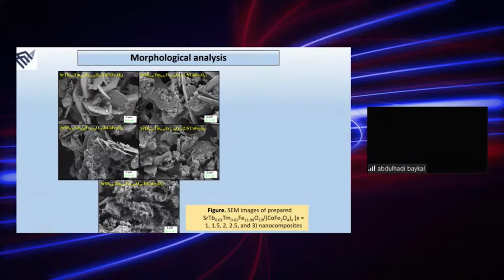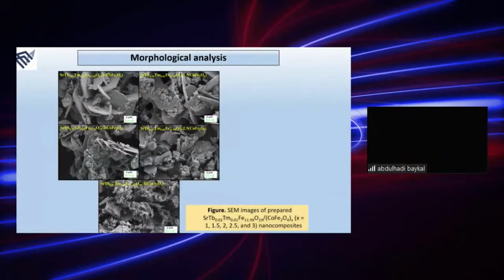You see, when we look here, it is clearly seen that there is a plate-like hexagonal structure in each of them, and then there are some other parts. This plate-like structure is due to the presence of the hexaferrite fraction, and the other part is due to the spinel part. You know that we have 5 products, and the SEM images of these 5 products are given in the slide, as you can see.